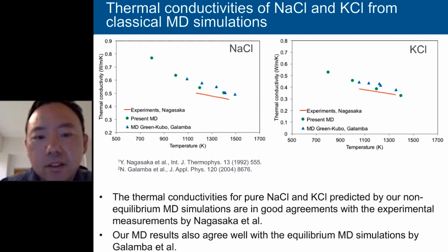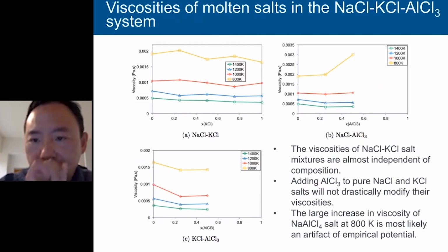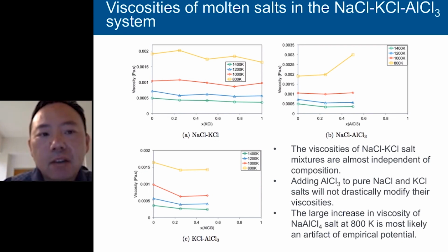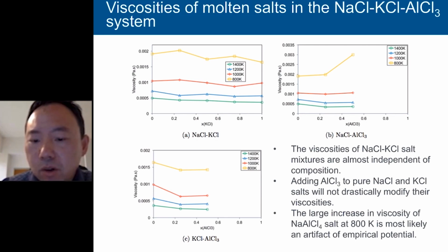So here the agreement between the MD simulations and experiments is excellent. Finally, I'm showing the calculated viscosities of molten salts of each of the 3 binary systems as a function of composition and temperature. You can see that the major conclusion is that adding aluminum chloride to pure sodium chloride and potassium chloride will not dramatically modify their viscosities. Actually, they even slightly decrease the viscosities. And also the viscosities of the sodium chloride and potassium chloride mixtures are almost independent of composition.